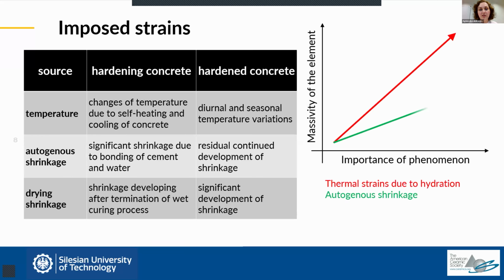The same goes for autogenous shrinkage, because even though this process is related mostly to the type and amount of cement, it is also a temperature dependent process. So if the massivity increases and the amount of heat increases, then the effect of autogenous shrinkage is also augmented in some way. On the other hand, drying shrinkage is a process that is inversely dependent on the massivity,